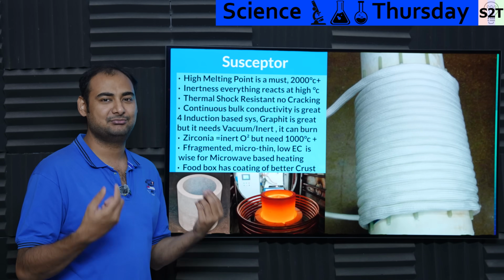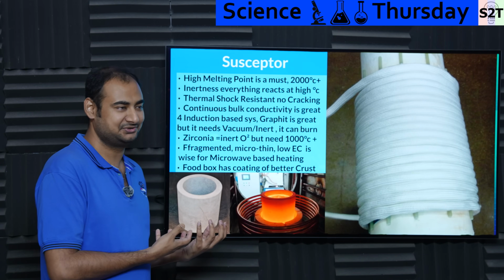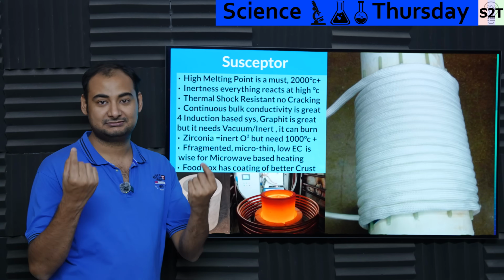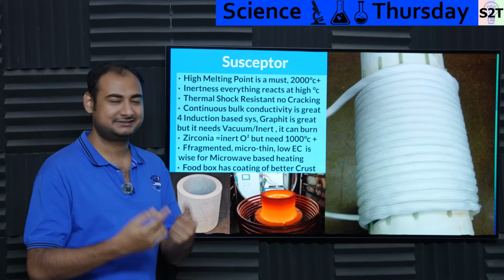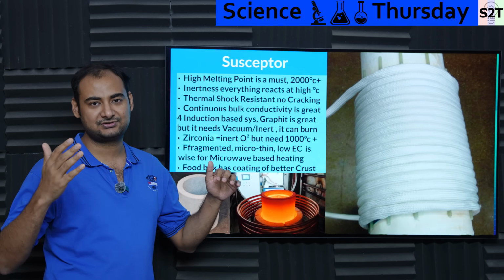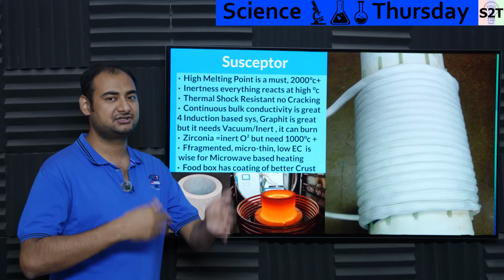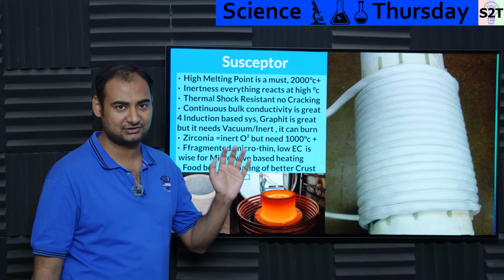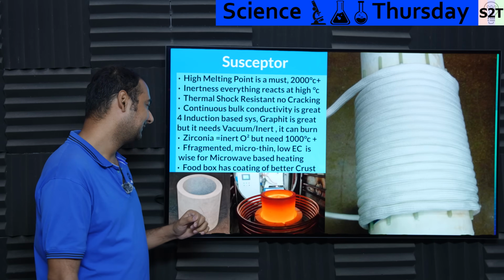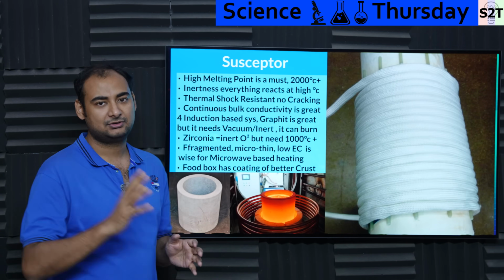My best guess is they might be embedding carbon particles into it, or have a graphite donut inside it. Because once it's above 1000 degrees, it will start to interact, then it will have a runaway reaction and you can easily achieve 2000 plus without any issue. And so far I've talked about induction.